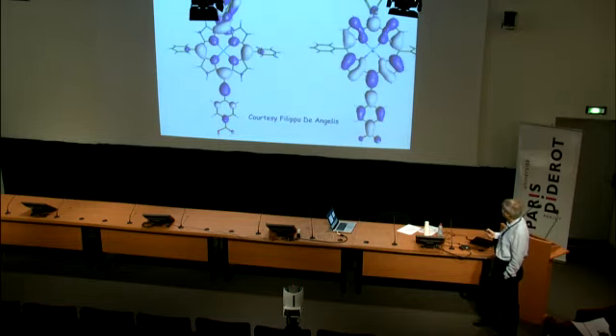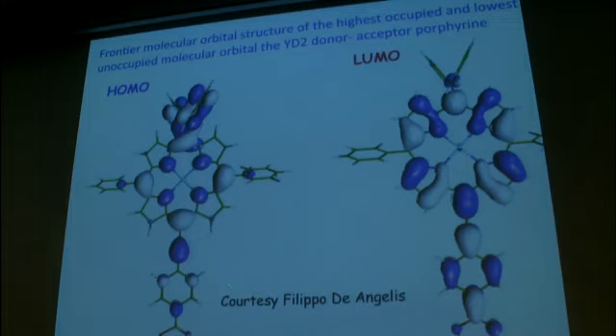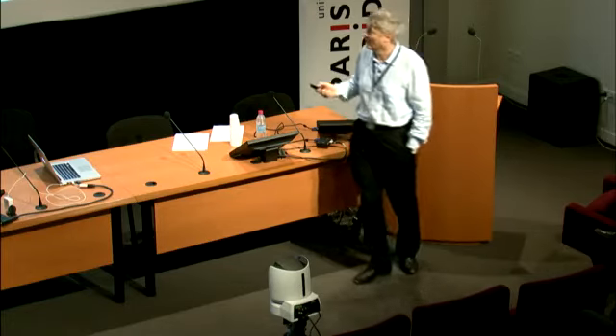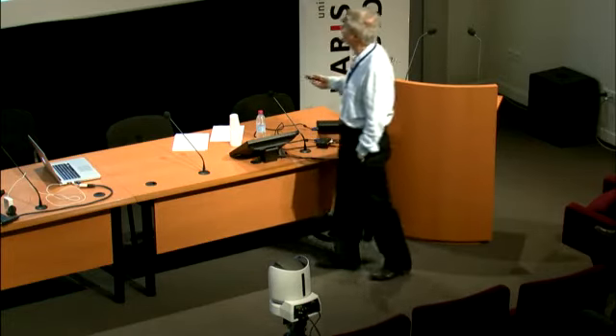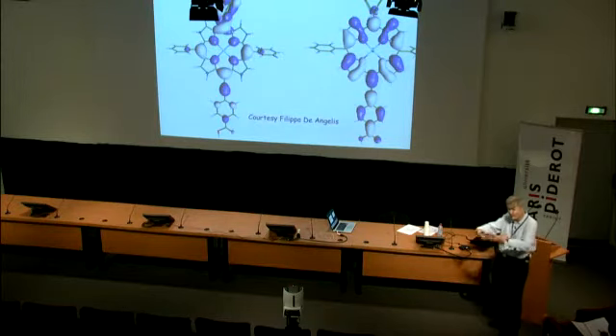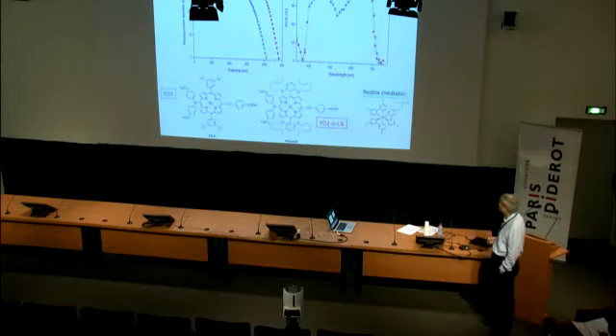If you do the calculations, Filippo De Angelis from Perugia did the calculations. You see the HOMO is now on the donor and the LUMO is on the acceptor, and they couple to the pi-pi star transition. It's not a pi-pi star transition in the porphyrin alone, and you get a very nice